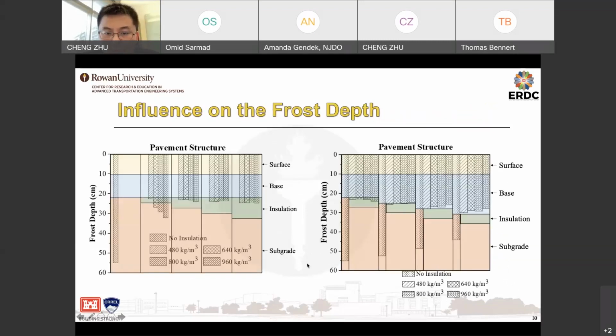So these two figures show the influence comes from these two factors. The left figure is showing the insulation layer thickness. The green color here indicates the insulation layer. As you can see, when the insulation layer thickness increases, the frost depth actually decreases. This bar chart here indicates the frost depth. With a relatively thin insulation layer, the frost depth is larger, and then it gradually decreases.